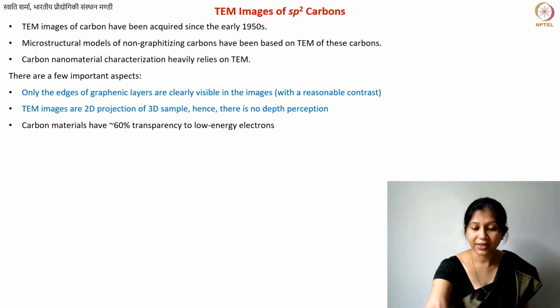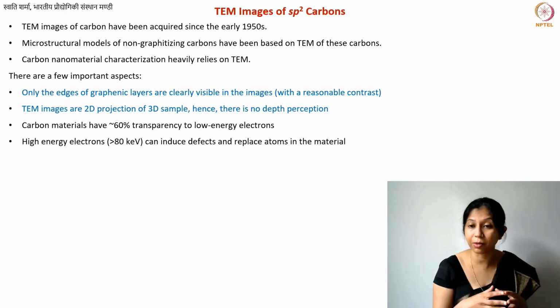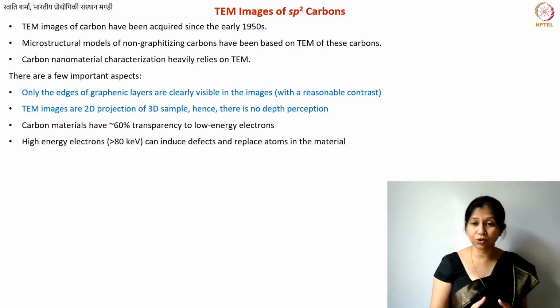Okay, fine. So as I said, carbon materials are transparent to X-rays and to various other wavelengths, but also for electron wavelengths, they do have a reasonably high transparency, especially for low energy electrons. But we need to use low energy electrons, because high energy electrons damage your sample. So most of the TEM equipment that are available often operate at 300 kilovolts, but you can go down to 100, but it's really difficult. In fact, a lot of instruments do not allow you to go below 100 kilo electron volts. And the optimum voltage is below 80 kilovolt.